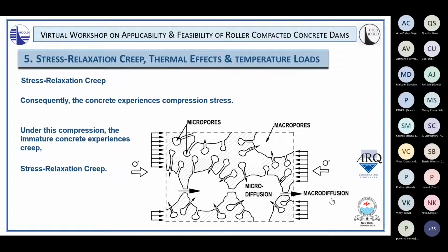So these macropores are caused by chemical shrinkage and autogenous shrinkage. The difference between the chemical shrinkage and the autogenous shrinkage takes the form of micropores being created within the paste. And as that paste then experiences compression, moisture from the micropores is squeezed into these voids that are the macropores, and in that process, the paste within the concrete structure collapses a little bit and relieves the compression stress that it's otherwise experiencing, and in the process shrinks.